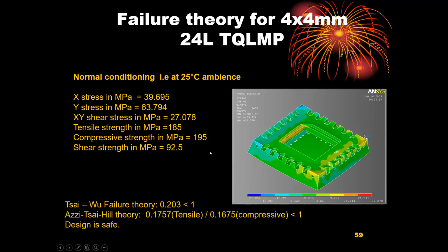The Tsai-Wu failure theory actually was applied, and then the Tsai-Hill failure theory was also applied. And we were pretty happy with the application of failure analysis theory after considering the moisture attack things. So when you consider the wet TG formula by Shamis and then evaluate the tensile, compressive, and the shear strength versus temperature with saturated moisture equilibrium, assuming steady state saturated moisture rate equilibrium, then we could apply the failure theory after modification and then find out whether it would be a problem at 25 degrees Celsius or 50 or 100 degrees Celsius. And that's what we did.